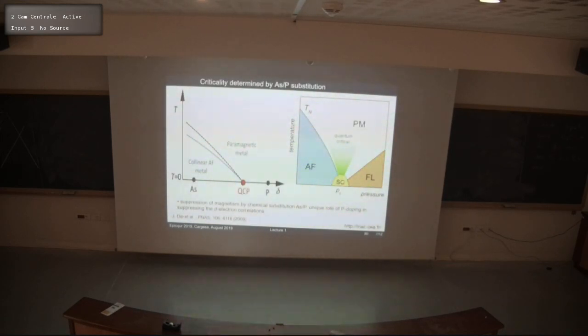And this is obviously, like in other strongly correlated systems, criticality can be found if you tune one parameter, especially, in this case, if you tune magnetism close to 0. One expects that one could find a quantum critical point, and it will give unusual metallic behavior and divergence in certain properties. In this case, the arsenic-phosphorus substitution is considered a good way to tune because you don't add doping, so you keep the system quite clean, and you can reduce the bandwidth in this way,